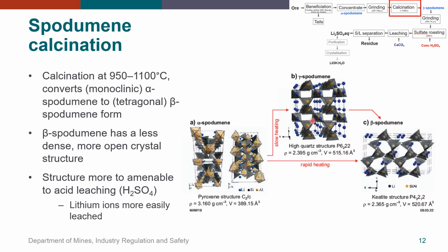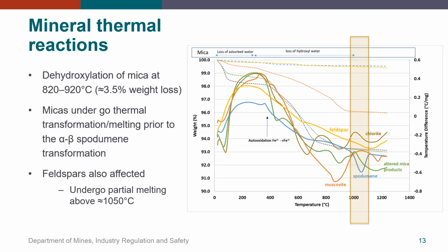Transformation of alpha spodumene to beta spodumene is necessary, as the beta spodumene phase has a more open, less dense crystal structure. This makes it more amenable to acid leaching, and therefore lithium is more easily extracted during the leaching stage. During calcination, other mineral and alteration impurities may also undergo thermal reactions.